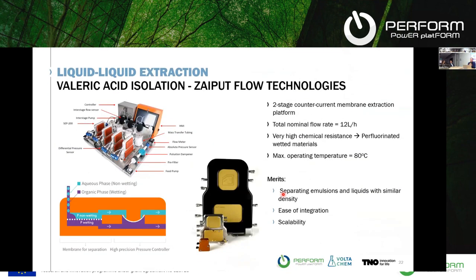If we look at the valeric acid side, valeric acid is a liquid, so we need all different separation techniques. What we came up with is liquid-liquid extraction. Valeric acid is in a water solution, and we mix this water solution with a solvent, typically an organic solvent. This will make two different phases.